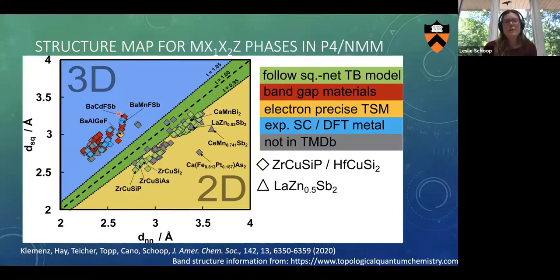And then we find some things which are ambiguous. The blue points, for example, are materials which are listed as metals in the database, but if you type this material formula, like barium manganese fluorine antimony, into Google together with band gap, you will find experimental evidence that these materials actually do have band gaps. So this points to a limitation of DFT, which this method is not vulnerable to. And then this orange point here is a material where, based on electron count, we would say this is either a topological semi-metal or a band gap material. We're not really sure, but it's listed as a semi-metal in the database. And then there are these gray data points. All these additional materials we can now categorize with these methods.